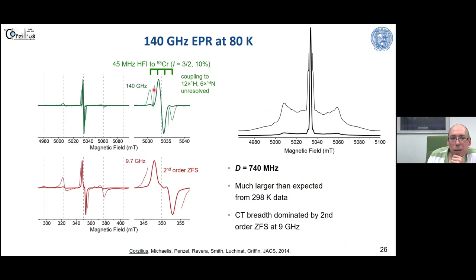You can see the 140 gigahertz and the 9.7 gigahertz, so this is typically X band. This is 5 tesla. You can see the influence of the external magnetic field on the second-order zero-field splitting. Here we have a rather large second-order effect on our central transition, and this is greatly reduced at higher magnetic field. At high magnetic field, we are not limited by this second-order effect, but, for example, by the hyperfine interaction to the chromium-53 nucleus, where we can see the hyperfine satellites of this quartet nuclear spin. You see nice, more or less resolved satellite transitions also. From this, you can determine the zero-field splitting constant, which is rather axially symmetric.